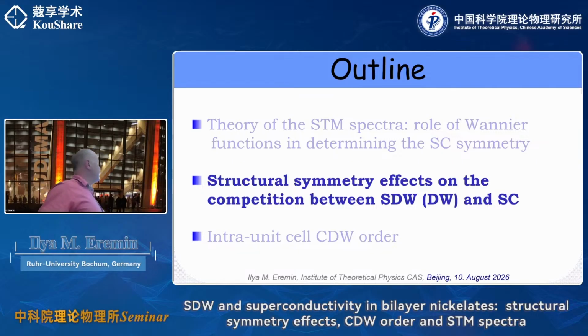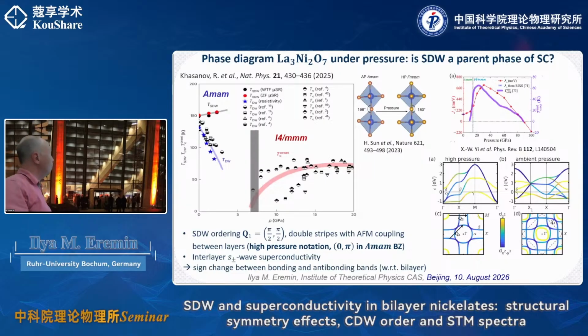Now, let's ask another question. Let's say we forget for a moment about the ambiguity about the structure. What is important is that whatever it is, I4/mmm or Amam, there is a spin density wave transition into the double stripe magnetic order. And as a function of pressure, these two transitions, which are about 30K apart in the parent material at ambient pressure, start to split. So the spin density wave transition is going up, the density wave transition is going down. I will be talking also about this. And then there is this I4/mmm phase.